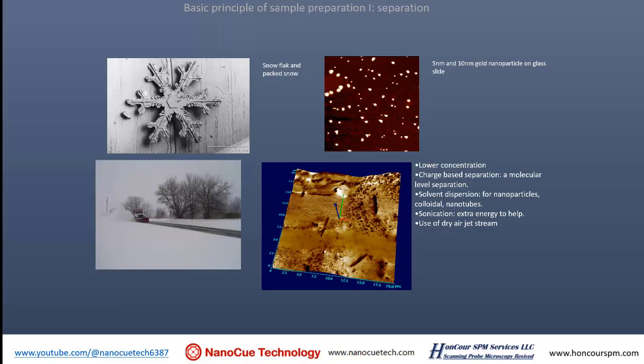You could also use solvent dispersion for nanoparticles, colloids, and nanotubes. It's relatively simple: you dissolve your sample in an organic solvent, for example ethanol, and then you could dilute it. You use the solvent to separate them. When you put a nanoparticle or molecule into the solvent, the molecules in the liquid solvent attach to and attract your molecules or particles, and when that happens, it separates them. So solvent dispersion is a very good way to achieve good separation between particles.